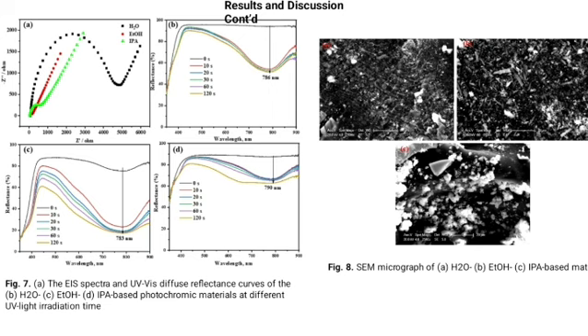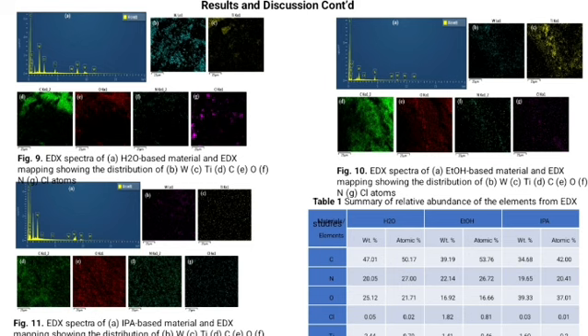which could give rise to electronic absorption and color formation. The EDS spectra and the elemental mapping also revealed the oxygen and nitrogen species were uniformly distributed in the compound, and they could be responsible for the transport of mobile electrons and holes for the photoredox reaction in the heterostructures, as revealed in Table 1 below.